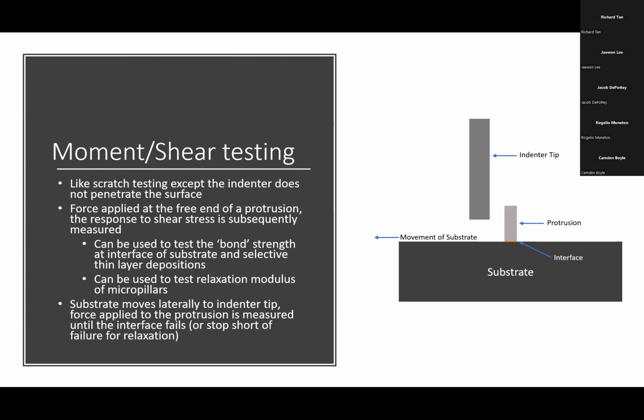The substrate moves laterally to the indenter tip. The force applied to the protrusion is measured until the interface fails, or if you're testing for relaxation modulus, you would stop short of that failure.